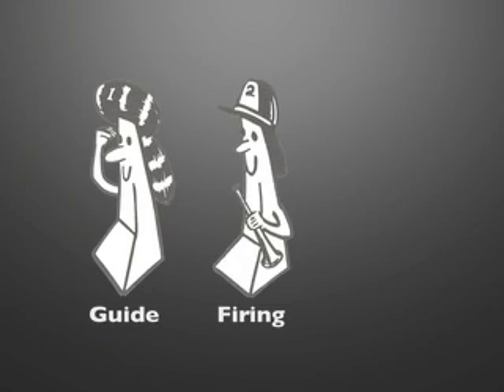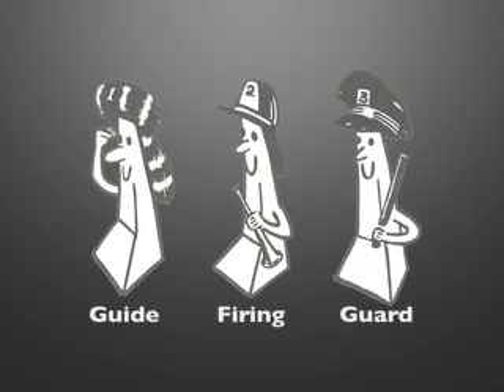Probably 2 or 3 cones would be best, and in some cases 4, depending again on the uniformity of the kiln that we're placing these cones in. If we use 3, we have the ability of a guide cone, a firing cone, and a guard cone. This then gives us the ability to find differences in uniformity within a fairly large range from top to bottom, or left to right, or front to back.